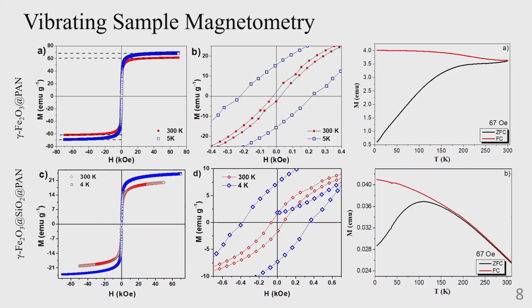At 300 K and 5 K, the MH curve for the maghemite with polyacrylonitrile sample is shown in this figure, and this corresponds to the values of the coercivity, the effective magnetocrystalline anisotropy constant K effective, and MS, by the equation of the law of approach to saturation.